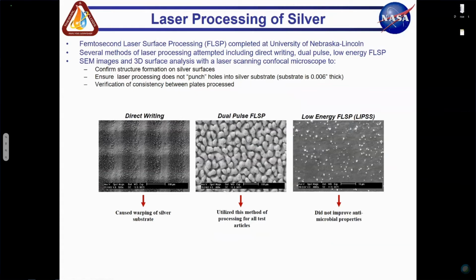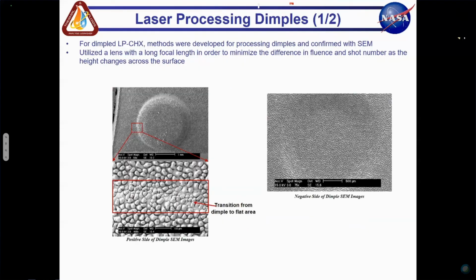The laser processing, I find the pictures really interesting. Looking at prior year's work as well, we looked at several different types of surfaces and laser processing patterns. There's direct writing, dual pulse, and low energy laser processing. We went with the dual pulse laser processing for this. We did a lot of SEM and 3D surface analysis on these surfaces, and we wanted to confirm that structure formation on this silver was consistent. We also wanted to make sure that our laser processing doesn't punch holes into that silver substrate. We were using about 6/1000 inch sheet of silver there.